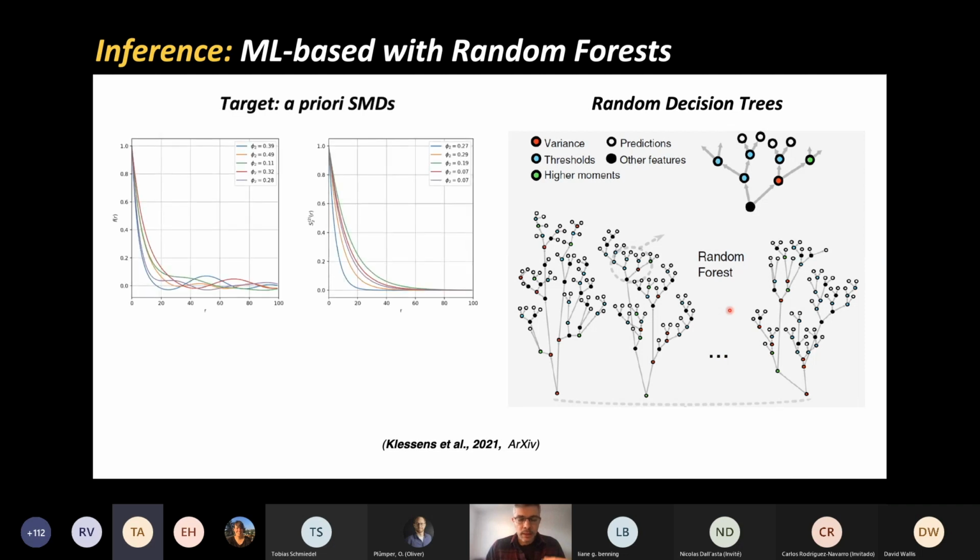When you have many of these trees, you can construct a Bayesian inference procedure that allows you to predict the output from the input. The way we do this for our problem is that we start with many 2-point correlation functions, for example, and here you see two types. These are Debye materials, and these are much more complex materials. We mix them, we predict their elastic properties, we feed them to these networks, and we train them to create these random forests. And from the random forests, this is the only equation I have for you. This is just Bayes' theorem. We can then create a prior here that we can give any data to and predict the posterior. That is an inference problem.